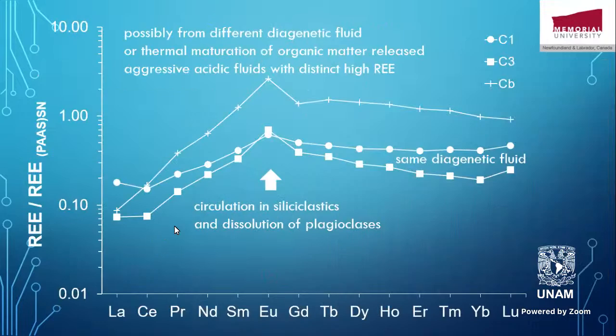Now, same thing. Let's apply the rare earth elements, normalized to the post-Archean Australian shale, as we always do. Look, you see that the same anomaly is almost gone. So it's not coming directly from water. So there's something new, possibly different diagenetic fluids, or thermal maturation of organic matter that released aggressive acidic fluids with a distinct pattern of elements. And you see again the positive europium anomaly, and it comes from the siliciclastics in the basin, with the circulation of the diagenetic fluids in the basin, where there are shale interbeds and some sandstone interbeds. And of course, this will result in the dissolution of the plagioclases, and this will make the fluids enriched in europium.